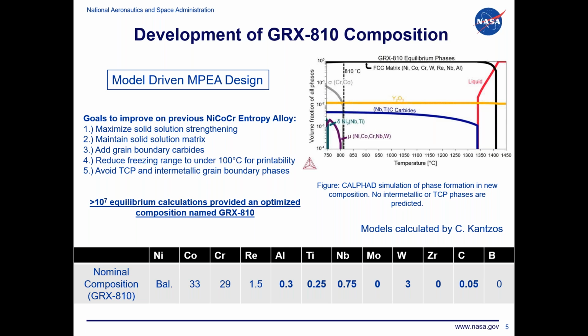So we used thermodynamic modeling to come up with a new alloy composition based around that nickel cobalt chrome foundation that we started with. And you can see the nominal composition that we came up with at the bottom here, which we were calling GRX 810.